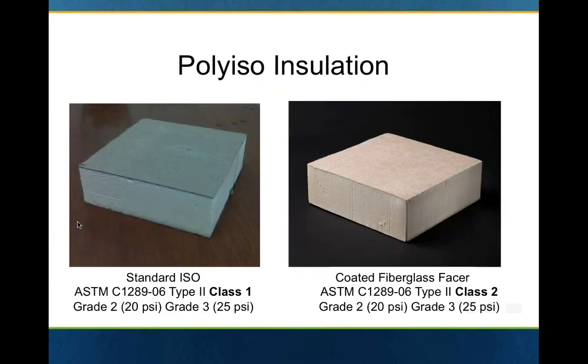For insulation purposes, polyiso has probably an 85% share of the overall market for low-slope roof insulation. And the ASTM is ASTM C1289-06 Type 2. There's Class 1 and Class 2 in 2 different grades, Grade 2 and Grade 3 for 20 PSI or 25 PSI. Class 2 would have a coated glass facer on it, which would be moisture-resistant and mold resistant, versus Class 1, which is a fiberglass reinforced organic facer.